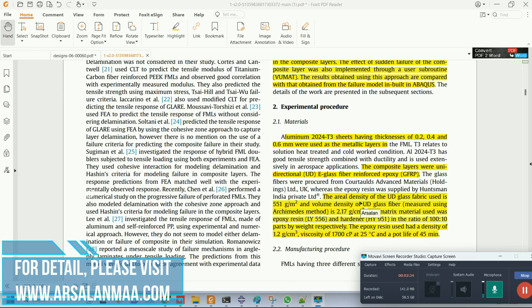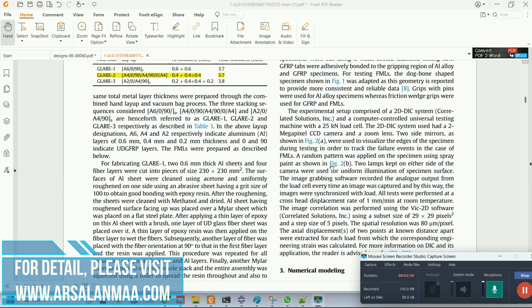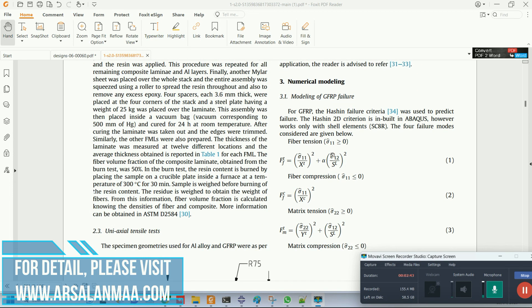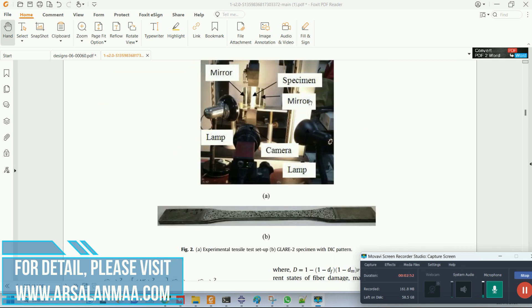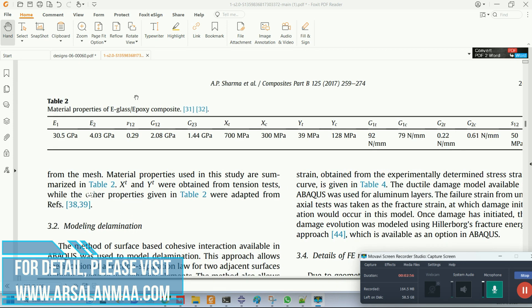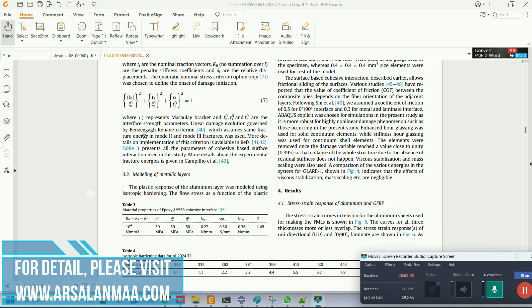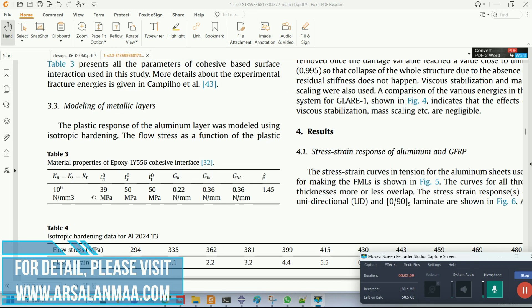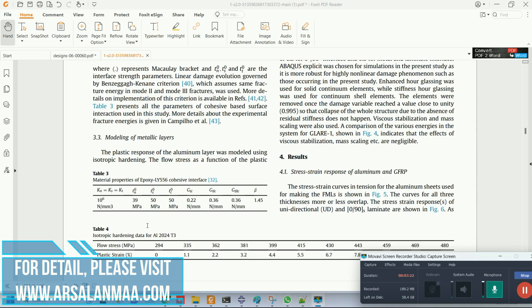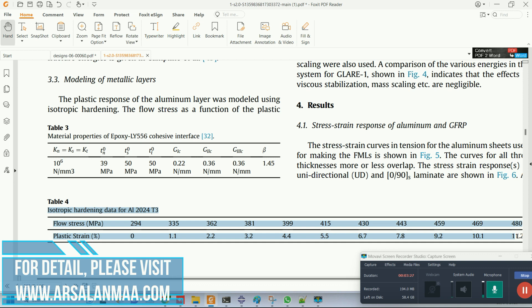These are the material properties of the composite as well as the aluminum layer. The numerical modeling procedure involves evaluating the GFRP, which is bonded together using the aluminum layers. These are the properties used inside the Hashin damage criteria to model the GFRP composite, and the delamination is modeled using traction separation laws. Based on the flow stress response of aluminum, we will evaluate the stress-strain response as well as the ductile damage parameters: fracture strain, stress triaxiality, and fracture energy.